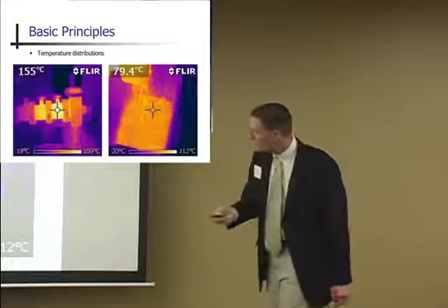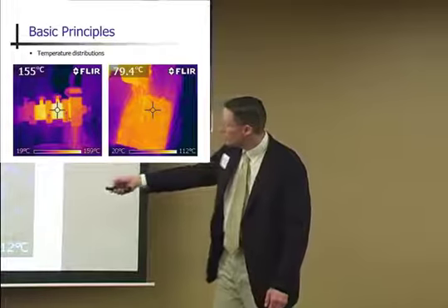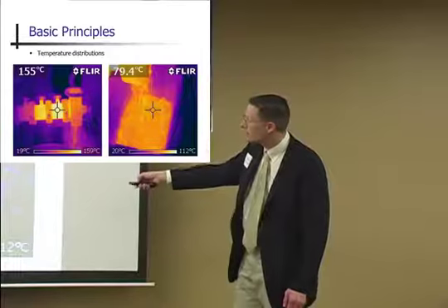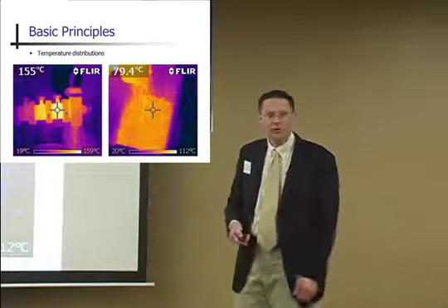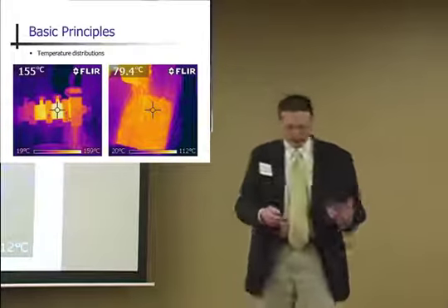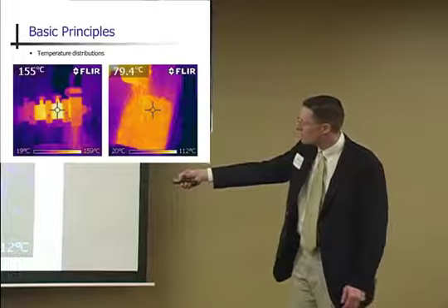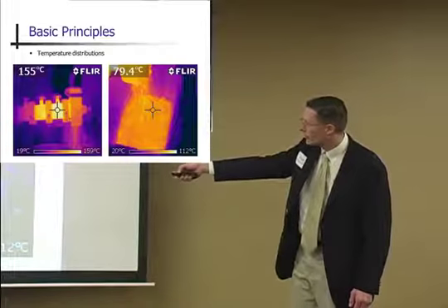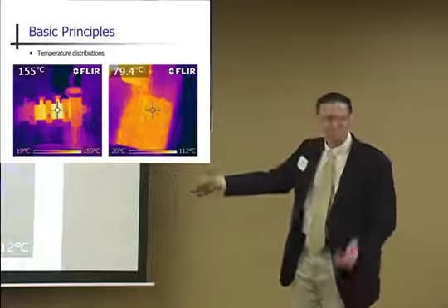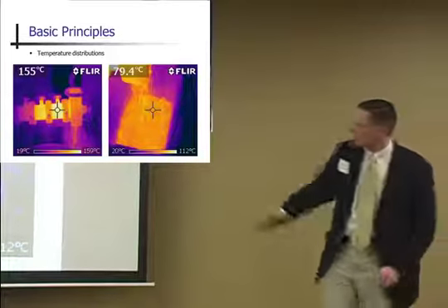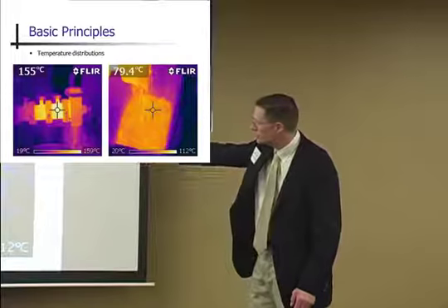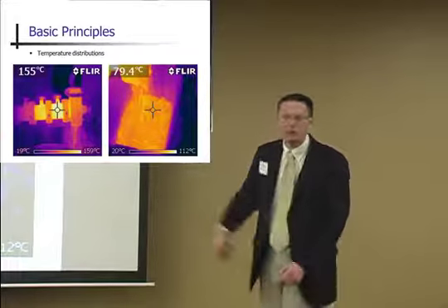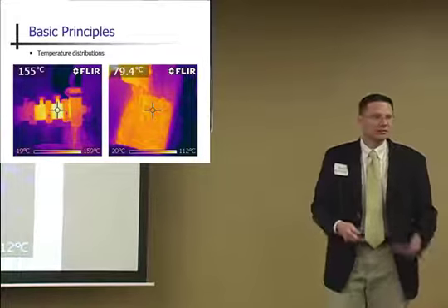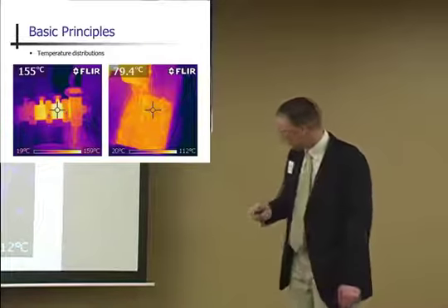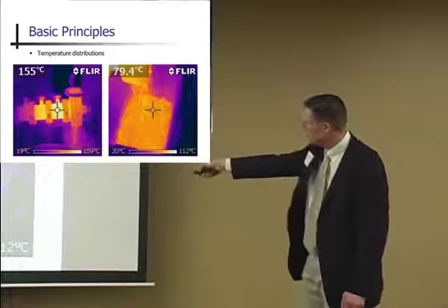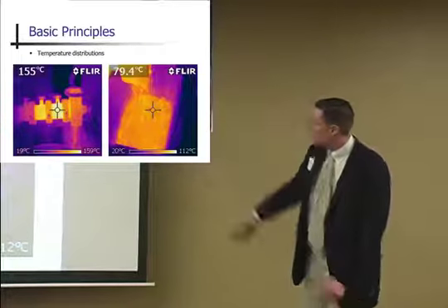Now, this is a picture of a study I just did last week. This is that InstaPro that I was showing you. No water, no steam is added, purely due to friction. And we see the ingredients are added over here at about 19 degrees Celsius. So it was room temperature. And then in about a 2-foot section there, we ramped up to almost 160 degrees Celsius, purely due to friction. And then these are the extruded pellets as they were falling out of the discharge.